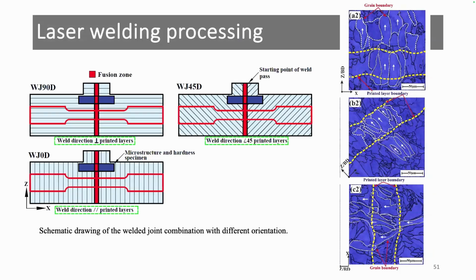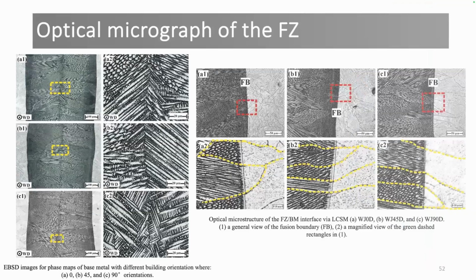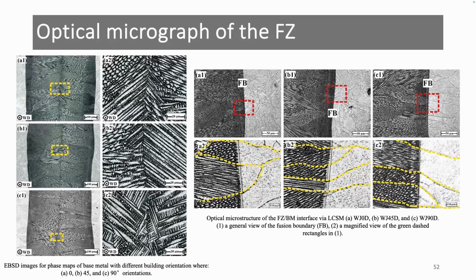We start with laser welding results. Here we just remind you again that for WJ90D, the welding direction is perpendicular to the printed layer. For WJ0D, the welding direction is parallel to the printed layer. Here is the optical microstructure by laser microscope of the fusion zone, and here is part of the base metal. When we look at the base metal, we will find that the cellular structure nearly disappeared after the heat treatment.